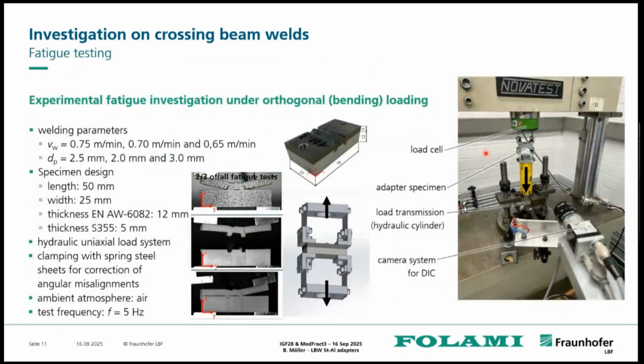Coming from this, we went into first testing, with some optimized parameters, and decided on welding speeds of 0.75 meters per minute down to 0.65, so not a quite wide range, and penetration depths resulting from this between 2.0 and 3 millimeters. These tests were then performed in a servo-hydraulic test rig under this orthogonal bending loading, as we called it. So pushing the two sheets away from each other and coming to a final failure where cracks initiated from the root towards the steel material due to this bending of the two sheets.